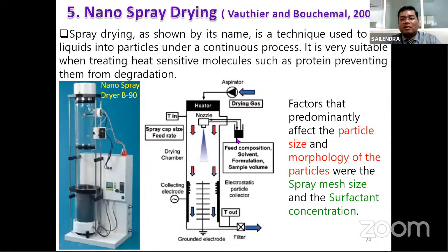Next method, and one of the most useful methods when you are going to prepare nanoparticles on a larger scale. Now you want to prepare industrial scale nanoparticles. At such a large scale, you have to do it by nanospray drying. This is nothing but you are going to have a concentration of this nanoparticle solvent where it has precipitated. Along with that, you will be having an organic solvent phase and the aqueous solvent phase. Both will be mixed. And they will be inserted into the chamber with the help of a nozzle at a very high speed.